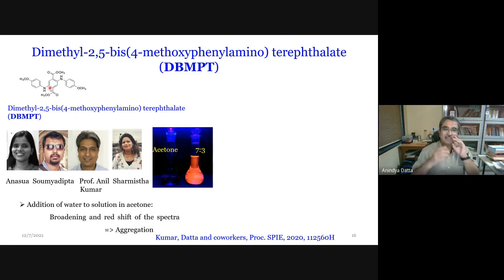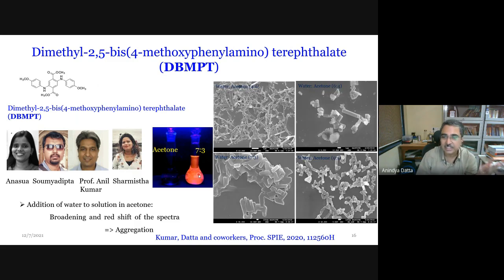Now, DBMPT once again has a very flexible structure, and associated with all this motion are plenty of non-radiative processes. So if you can quench them, if you can stop that motion, you can hope to get fluorescence. And that's what we see here in acetone solution. Acetone is a good solvent for this molecule. There is no fluorescence. If you add a little bit of water, then first of all, the mixture becomes turbid, and we get significantly stronger fluorescence. We got sort of nanorods from this system when you added water.